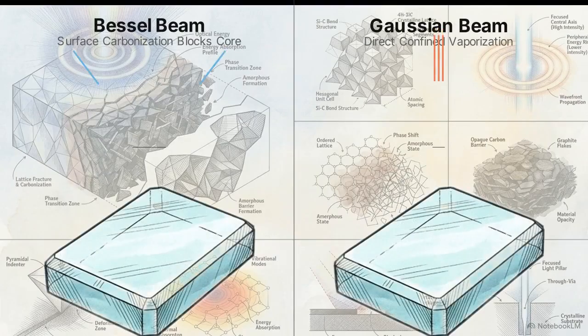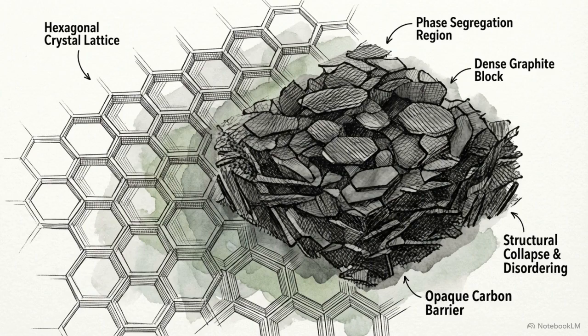A standard Gaussian beam does not possess these wide peripheral side lobes. The thermal energy is strictly confined to the central optical axis. This confinement vaporizes the material directly along the path of the beam before a peripheral graphitic shield can intercept the light. This barrier is a transient, localized material state rather than a static bulk property. Whether applying high-pressure shear stress or nanosecond thermal pulses, 4H SiC defends itself by segregating into the same graphitic shield.